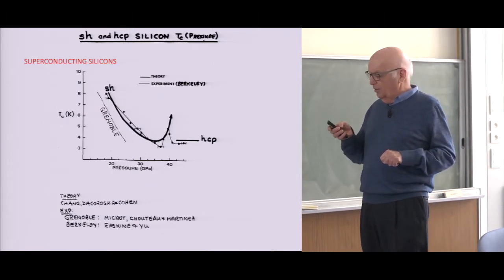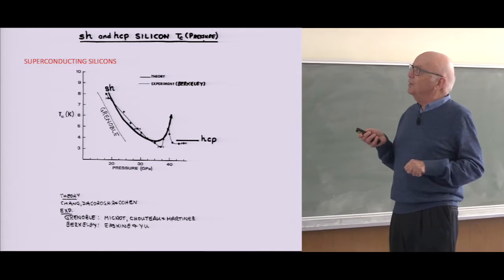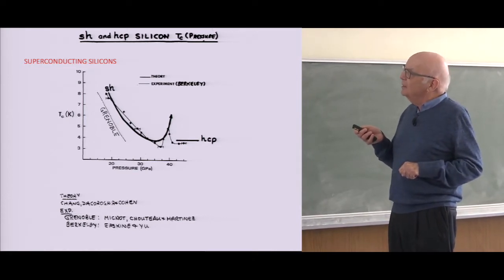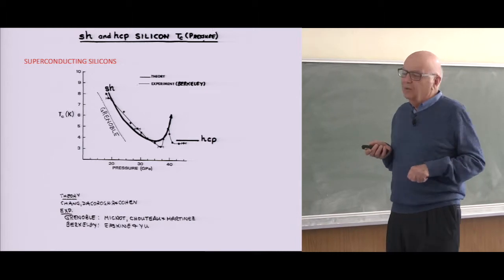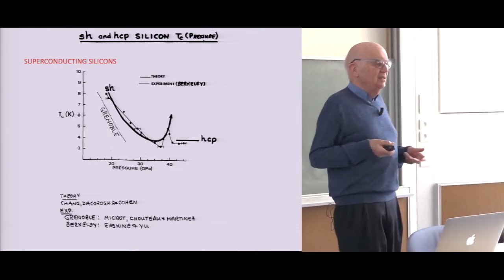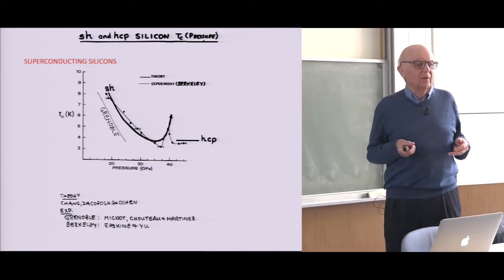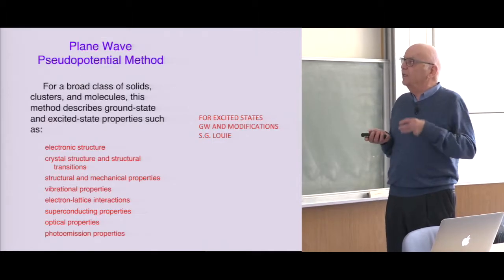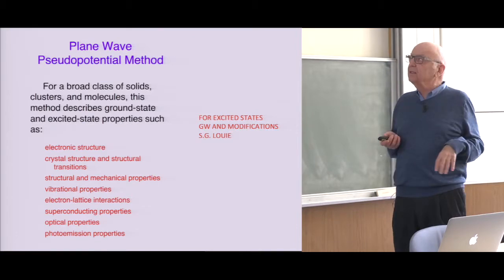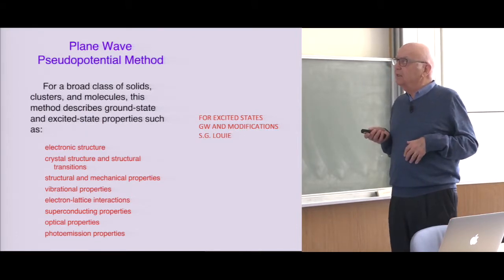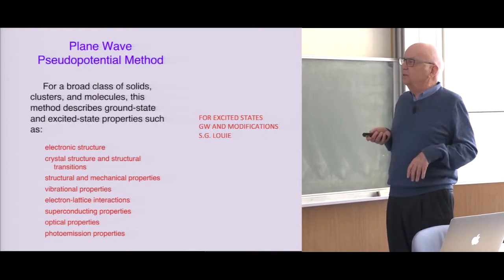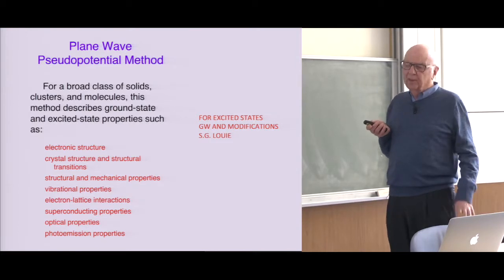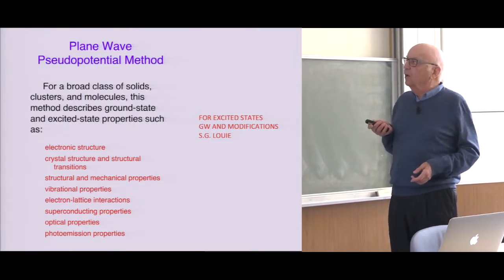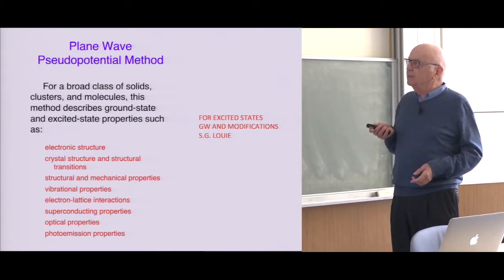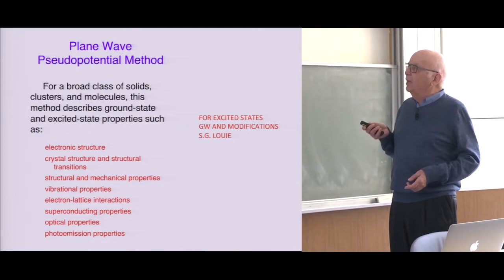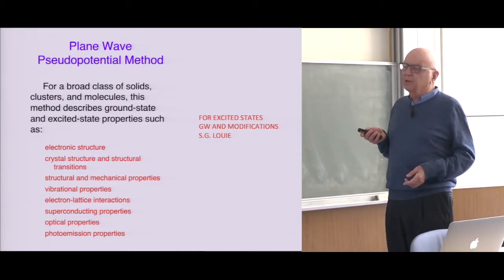Fortunately, my colleagues in Grenoble were the first to show that they were superconducting, roughly where the theory is, and then the experiment was refined, and you could show that you could predict superconductivity in a system that was not previously known, and you could make them. I'm going to use this later as an example. So the present state is that for a broad class of solids and clusters of molecules, and here I'm thinking of three-dimensional systems, you can use this plane wave pseudopotential method to give you the energies and the properties. All of these properties, structural and even excited state properties, using modifications like the so-called GW approach. You can also do optical properties.